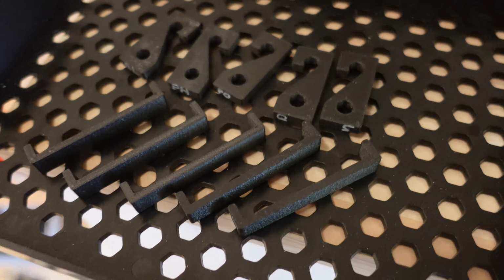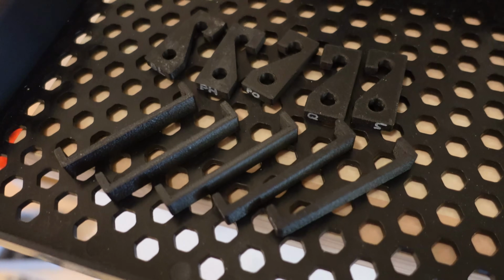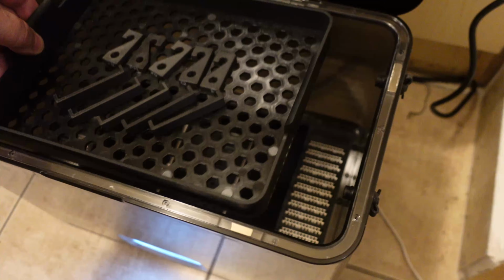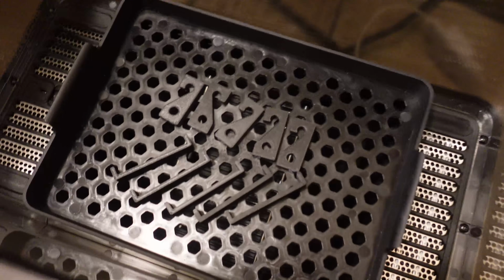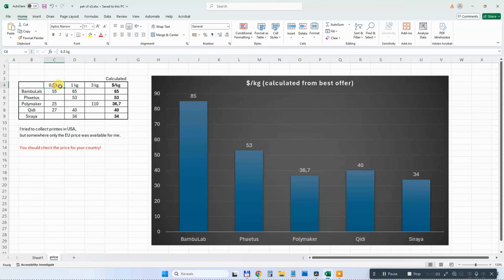The annealing will be done on the Sunlu E2 filament dryer. Temperature is set to 100 degrees Celsius and these are small test objects, 2 hours should be enough. They cool down together with the dryer. The price is very important. Now they have different spools, but I calculated the price for 1 kilogram using their best offer. The BambuLab is most expensive, then Phaetus, and the rest 3 are very similar.